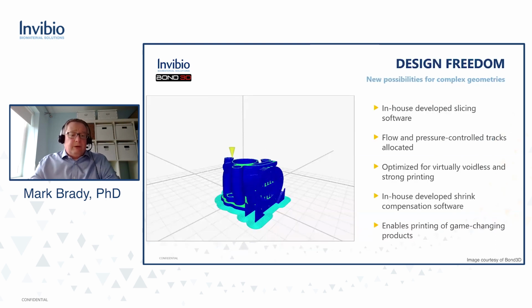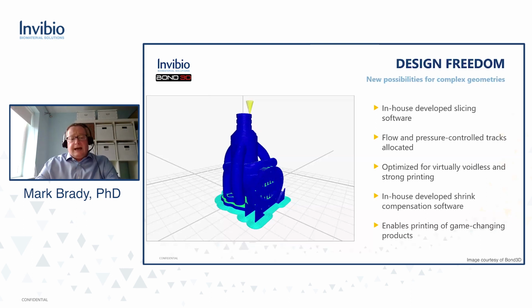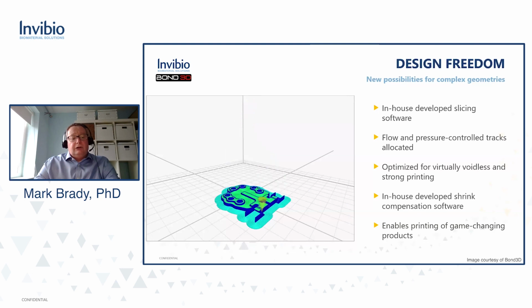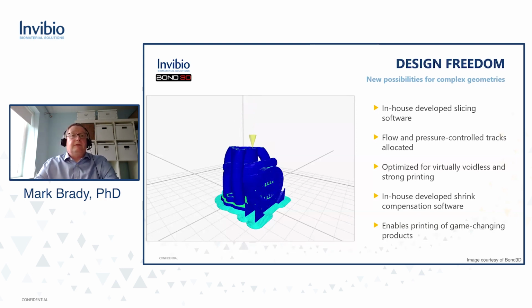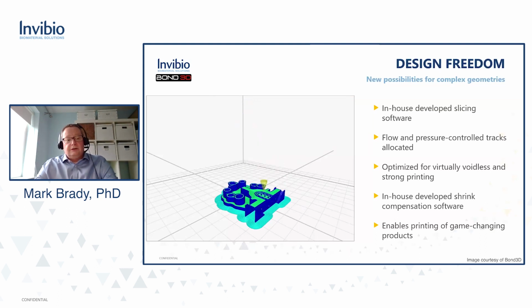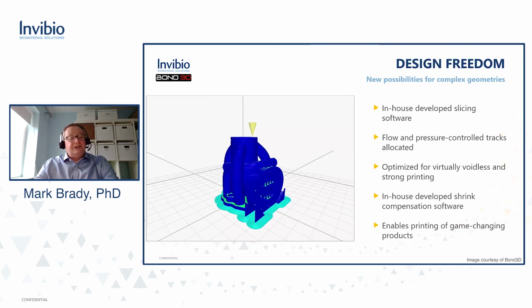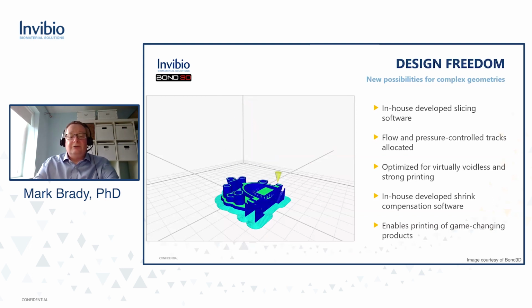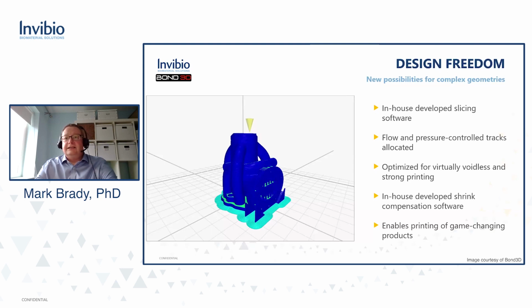The other element that Bond have developed in-house is their slicer software. The slicer is what takes the CAD model and the print parameters, for example, the layer height, the speed, the infill structures, and translates those into the G code for printing. They've needed to do this since the commercial slicers don't allow them to lay down these alternating flow and pressure control lines within a single layer. The process allows them to optimize that printing for virtually voidless and strong parts.